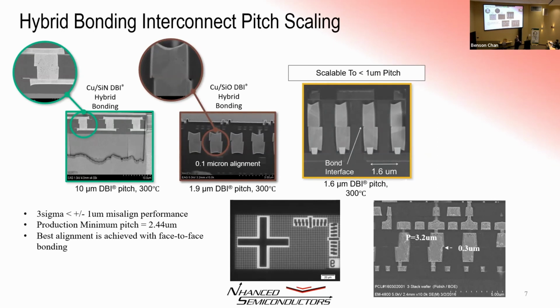Most of the layers are very thin. The pitch at which we can bond experimentally, we've delivered to a customer a 0.8 micron pitch. Our line is rated to 2.44 microns. And that's at wafer scale or at die to wafer. Literally, we use the same bonder for both. There's no difference.